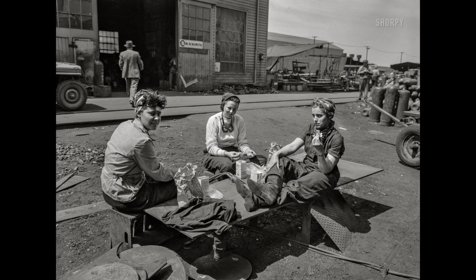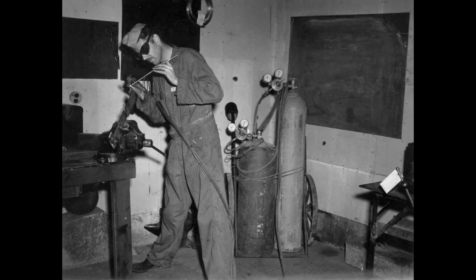The lieutenant shook his head. He said American yards were building 50-ton prefabricated sections that contained hundreds of welds and 0 rivets. These sections were lifted by cranes, positioned within fractions of an inch, and welded to adjacent sections. The entire ship was one continuous welded structure. If Italian engineers considered that risky, they misunderstood the mathematics. A properly made weld was stronger than the base metal. Testing proved it conclusively. The failures that occurred, the ships that cracked, resulted from poor steel quality or design errors, not welding itself. Fix the steel. Fix the design. The welding worked fine.